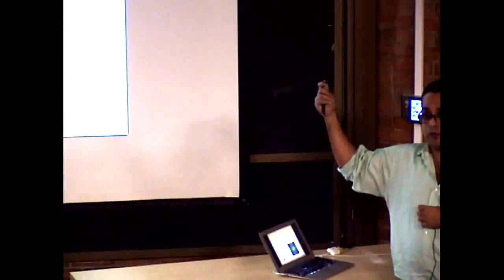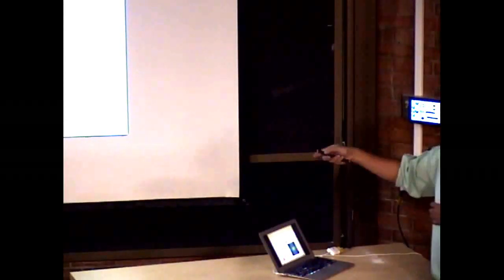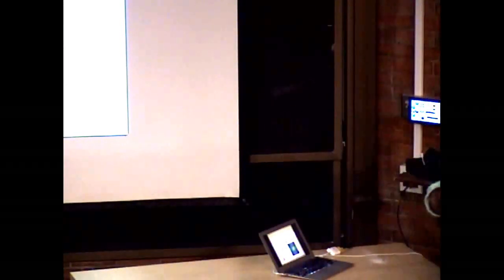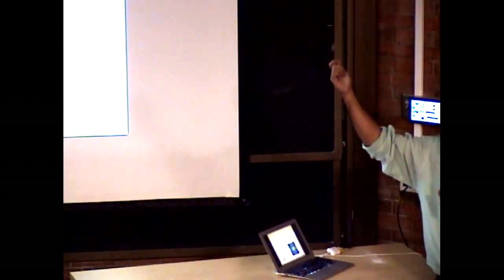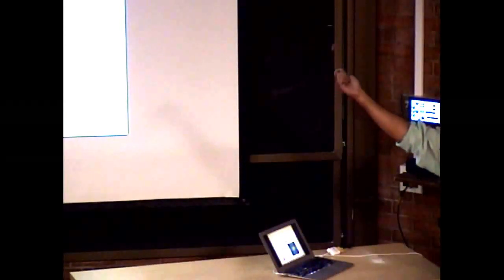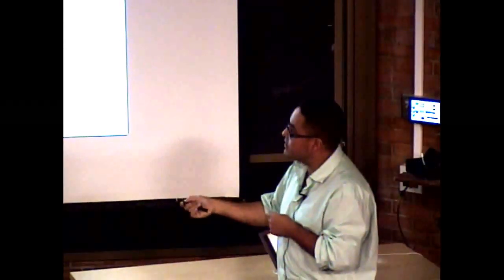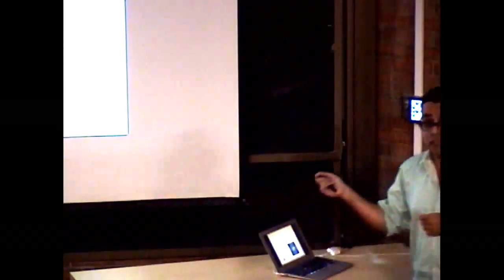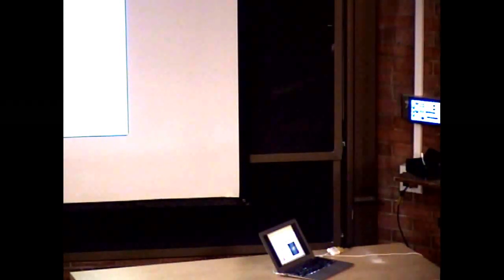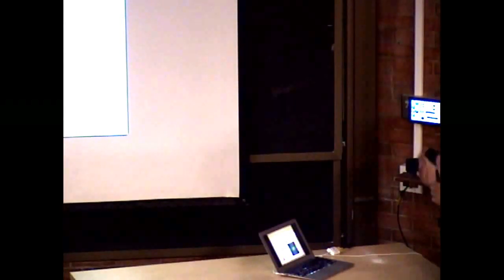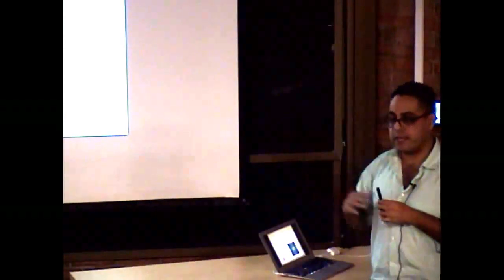Why do I need to do that? It's because now I'm going to look for a nonlinear coherent signature. So a photoluminescence that comes through an excitation pathway involving 4 pulses, in which I will generate coherences, project them to populations, regenerate coherences, and then regenerate a population to 4th order using this type of technique, but with a very well-defined phase pathway. Why do I want a very well-defined phase pathway? Because I want to be able to say I'm looking at a particular nonlinear response that is well controlled and well understood, that I can then analyze.